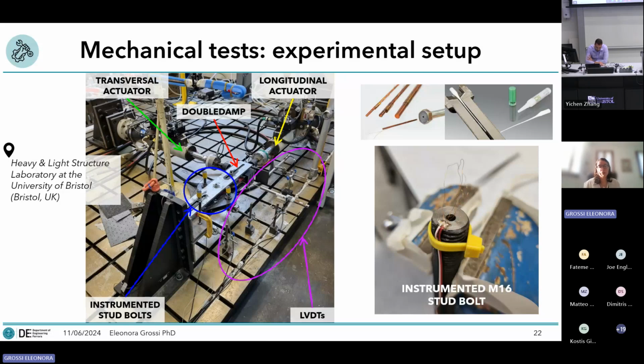The experimental setup consisted of 2 actuators tuned together to apply simultaneously a displacement in 2 different directions. And I applied several LVDTs to double check the displacement applied by the actuators and any misalignment of the device. And finally, I instrumented the stud bolts of the device. This was to monitor the actual force, the actual load on each bar. To achieve that, I inserted these cylindrical strain gauges inside a hole that I drilled within the stud bolts, and you can see here the wires coming out.